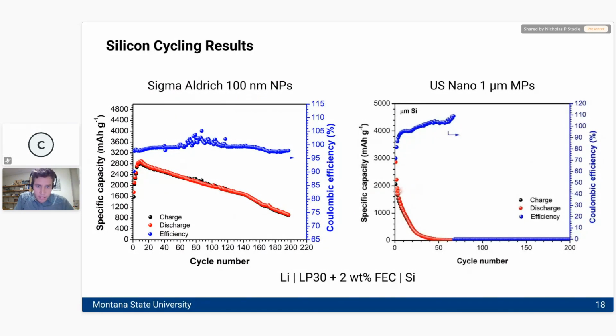On the right is a much more typical set of data. So this is a different supplier. These are 1 micron sized microparticles, and lo and behold, we get a decently high capacity on cycle 1, but then it rapidly declines and you get almost no capacity by the time you're at cycle 50. So just from the perspective of an experimentalist just cycling a cell, this silicon is behaving very, very differently from graphite.